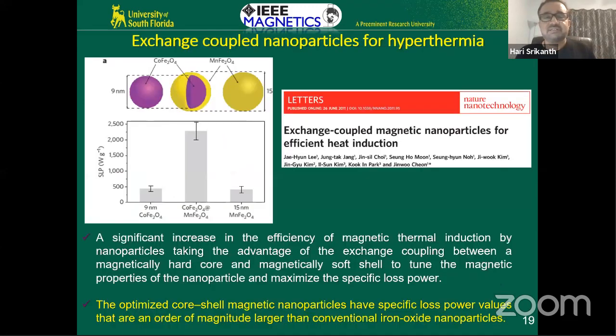So while we were doing this, we were scooped in some sense. There was a paper by this Korean group. They actually showed that cobalt ferrite, manganese ferrite, all oxide, no Kirkendall effect, stable core shell particles. They found that this is an exchange bias. Remember I told you about an antiferromagnet and ferromagnet having an exchange bias because of the interface. So these are all tiny exchange coupled spintronic nanoparticles, okay? And essentially they also showed a high SAR, indicating that indeed the exchange or interface anisotropy is important for this application. All right, so we tried this.